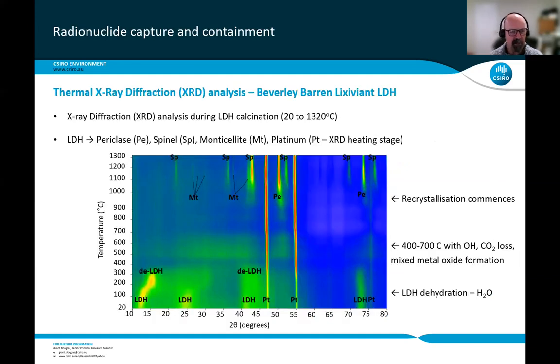So what does that mean in terms of the mineralogy? We've done a thermal X-ray diffraction analysis, and we go from about 20 to about 1,320 degrees. And we've got the layered double hydroxide, and just for your note, the periclase here is known as PE, spinel, SP, monticellite, MT, and the platinum is actually the platinum heating stage. And that's those 2 bright red lines that go from the bottom to the top of the diagram. So in that diagram, it's basically just a heat map, blue, cold, red, hot. You've got temperature, as I said, from 20 to 1,320 degrees, and you've got the angle, the 2 theta degrees